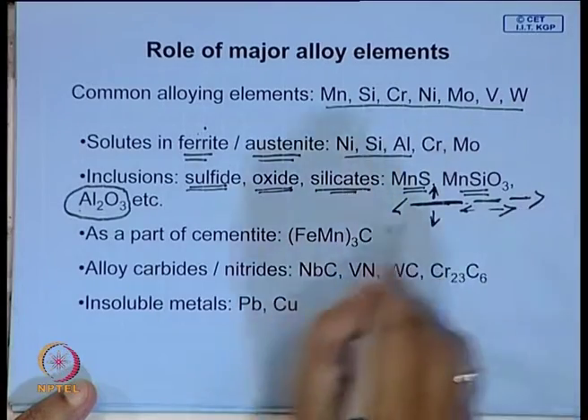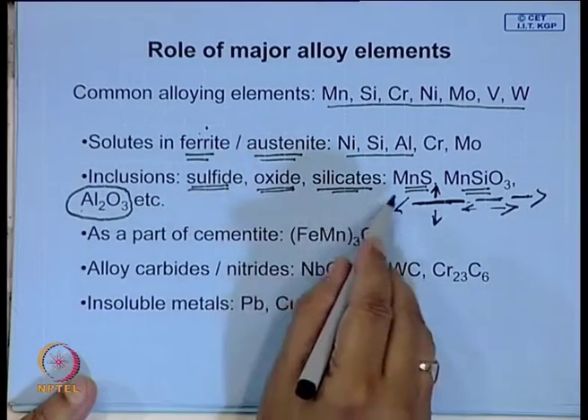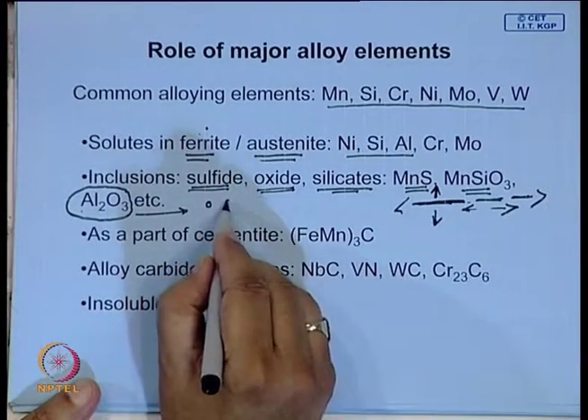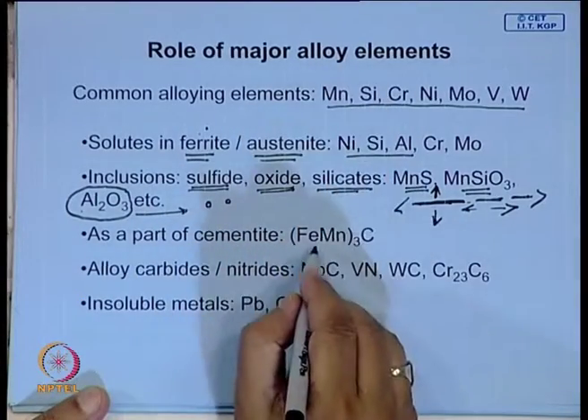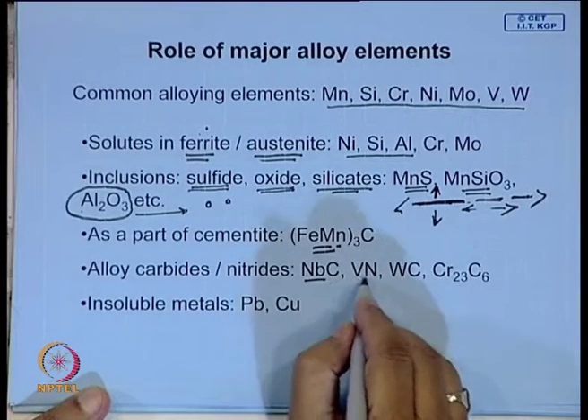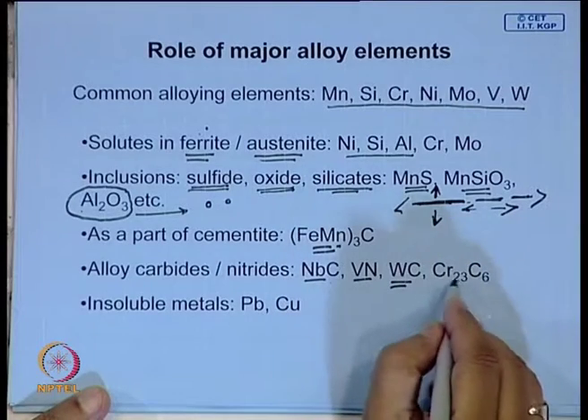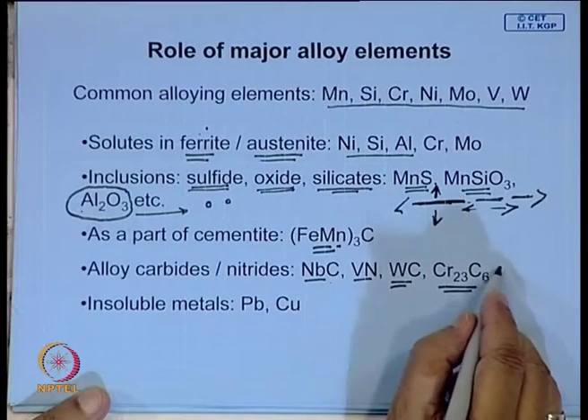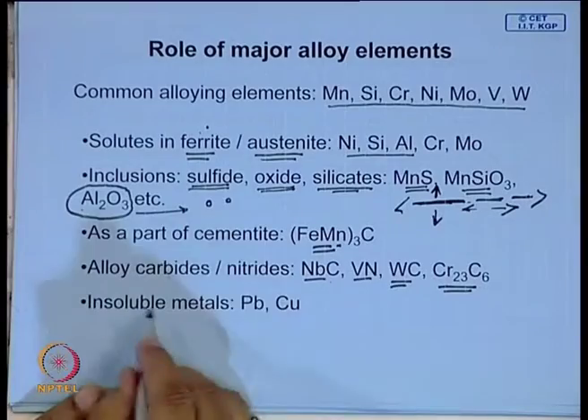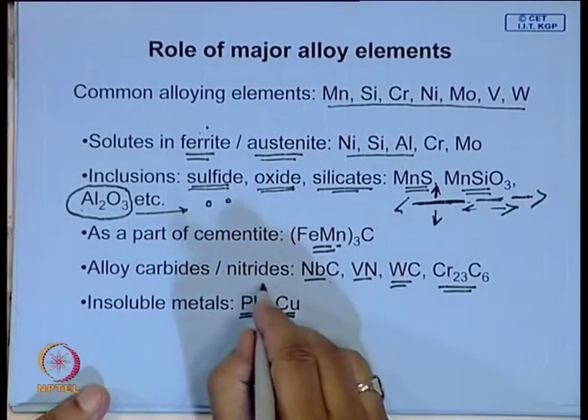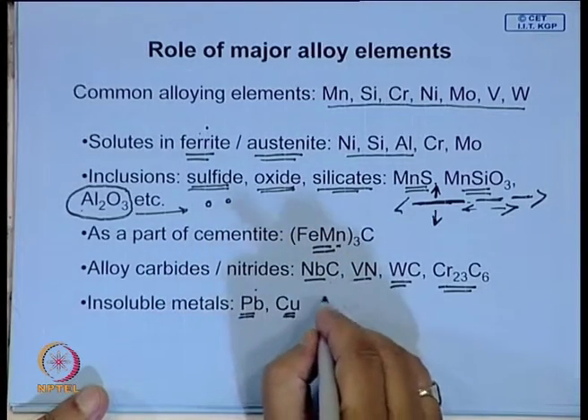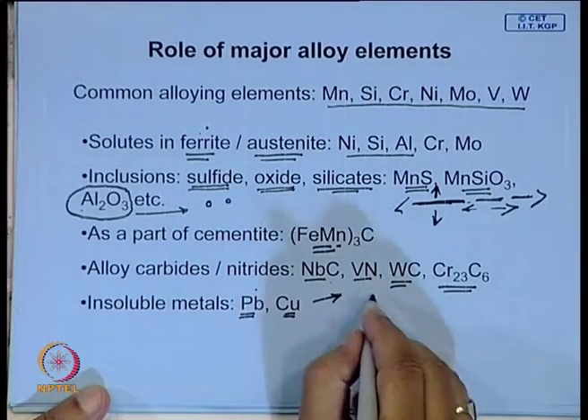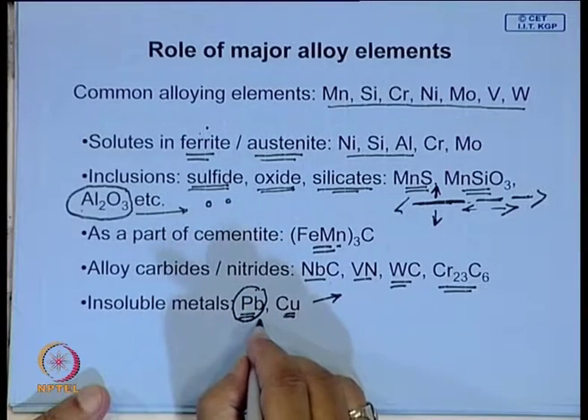So, inclusion control becomes necessary; shape and size control of inclusions is key to improving properties like weldability or transverse strength, whereas these are hard particles present as globules. Some of the elements may dissolve in cementite, and many elements, as we have seen, you add: niobium, which forms carbonitrides, vanadium nitride, tungsten also forms carbide, moly also forms carbide, then chromium also forms carbide. There are certain metals which are added, like lead and copper, that are insoluble. So, they are present as globules of lead or copper. Copper is added to some precipitation hardenable grades of steel, HSLA steels, and lead is added to steel to give it good machinability.